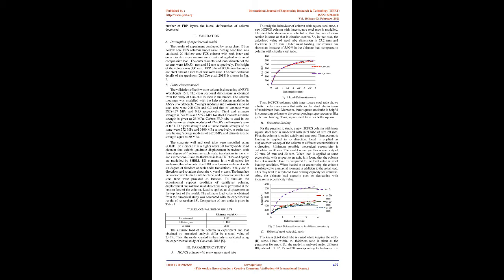Improved flexural capacity was observed for the HCFCS column. The flexural strength of the column was found to increase with the confinement, strength of concrete and the applied load. Outward local buckling of the steel tube was delayed because of the presence of concrete filled between FRP and steel tube. Under lateral impact loading also, the HCFCS column behaves in a ductile manner. With increase in the number of FRP layers, the lateral deformation of the column decreased.